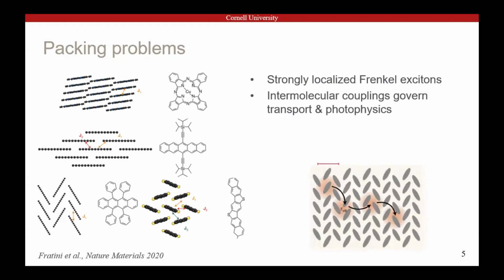If you need to transport through nearest neighbor hopping, the best thing you can do is radically increase the coupling between nearest neighbors. So people have come up with motifs to have these very strong one-dimensional stacks or two-dimensional stacks, these three-directional couplings. So there are lots of packing regimes where you can maximize the number of strongly coupled neighbors between molecules to kind of boost the integrals that govern this transport. So you may be problem solved.